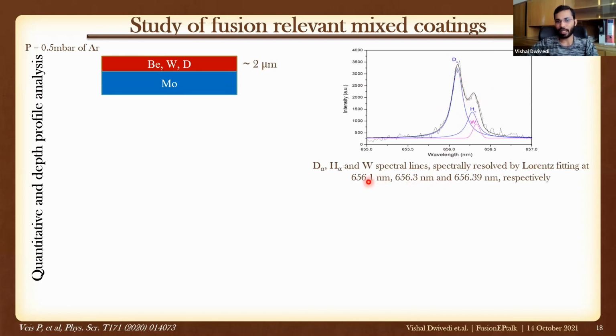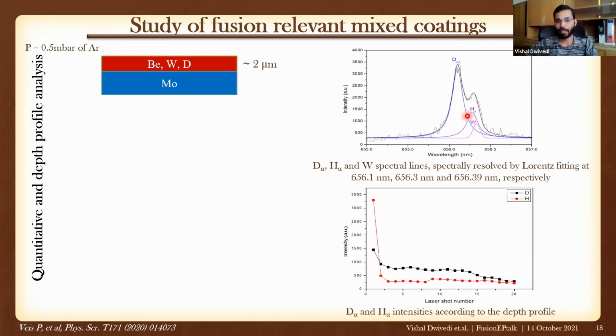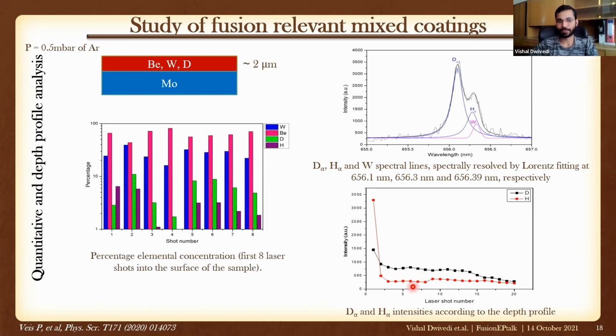And these are the spectral lines, 656.1, 656.3. Also, this sample contains tungsten, so we can see the tungsten line here too. We should be quite careful in the deconvolution of this spectral line to obtain the D/H ratio for a clear and precise composition analysis. We calculated the D and H intensity with the laser shot numbers, so we can see the decrease in the signal after several laser shots.